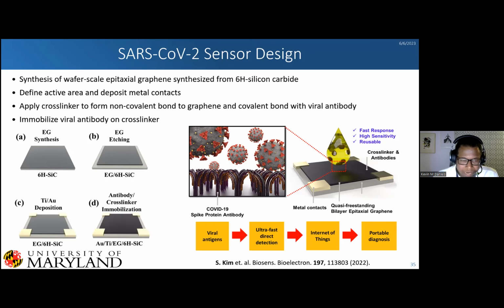And my postdoc Saram, he was like, no, let's try it, because at the time we had done gas sensors that had shown response and recovery times in seconds, and so yeah, the rest is kind of history. And we fabricated these devices. So very, very simple fabrication process. You have a graphene synthesis. We etch the edges away in order to secure our Ti/gold contacts. As I said, graphene doesn't like to stick to things.